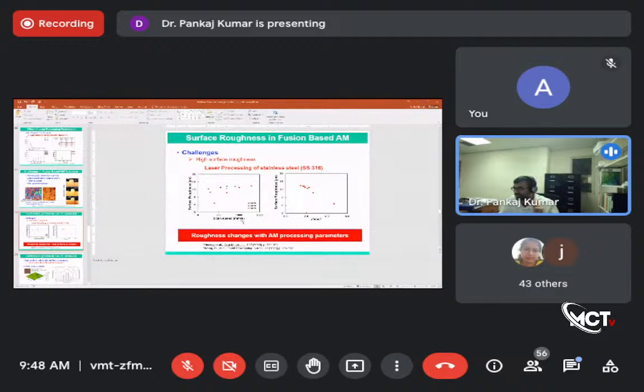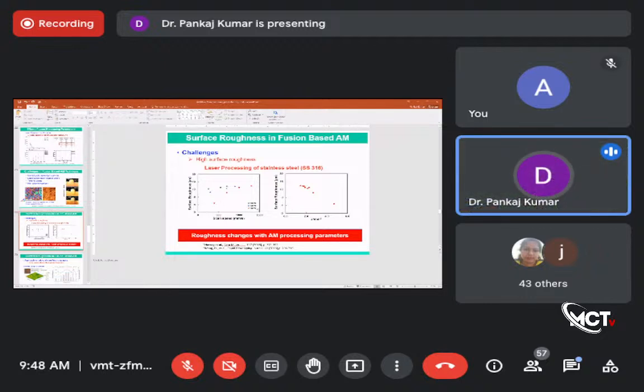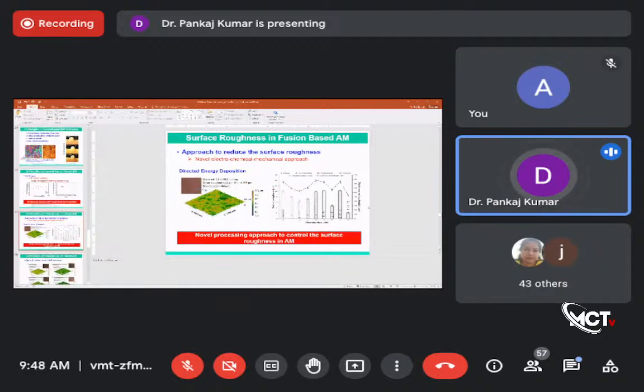And you see, this is an example for the stainless steel material. Depending on the parameter, your surface roughness can vary, right? For example, scan speed changes your surface roughness. You increase the scan speed, your surface roughness will increase, depending on what the laser power is. So all these parameters change the performance of the surface, right? So this is important. These are challenges we really need to take care of.